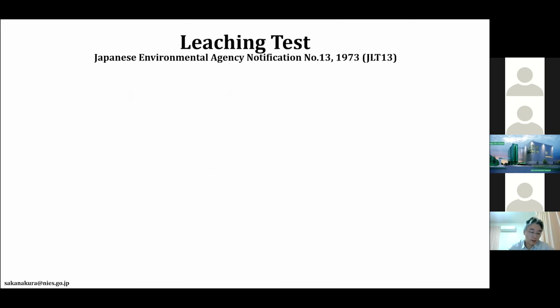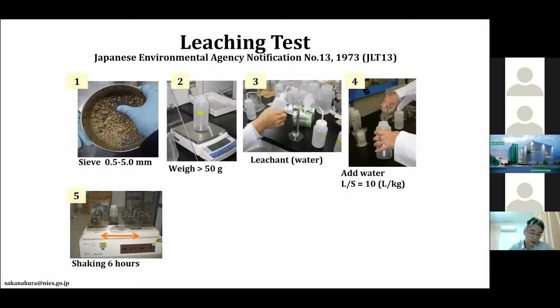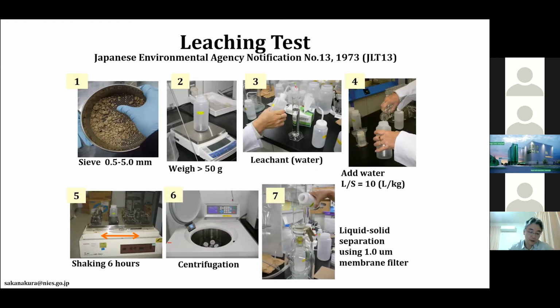The leaching test to be applied follows this procedure. The test is called JLT-13. After sieving the waste sample, more than 50 grams are mixed with 10 times volume of pure water. After that, the bottle is shaken for 6 hours horizontally, and the liquid portion is separated from the solid portion. The concentration of heavy metals and other substances in the liquid is determined by ICP, for example, and then it is judged whether the waste is acceptable at landfill.